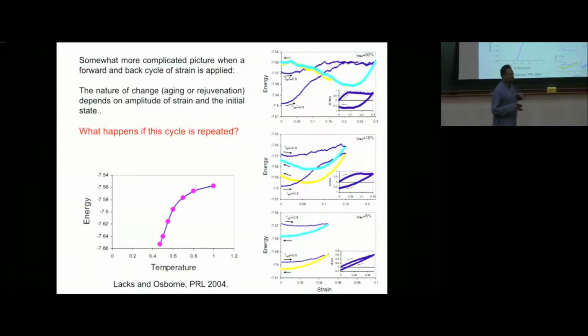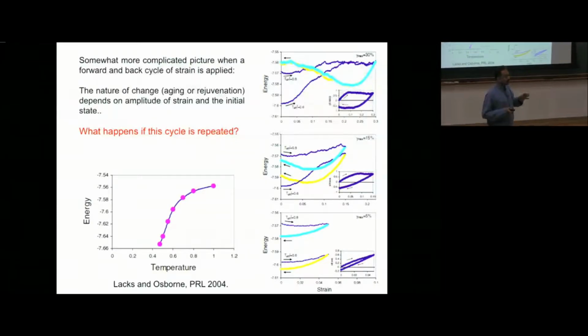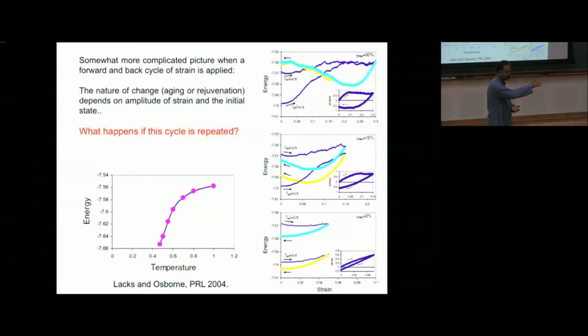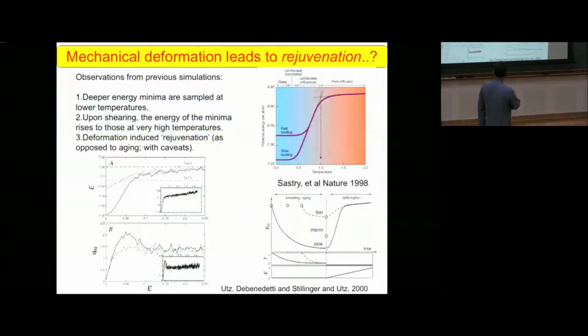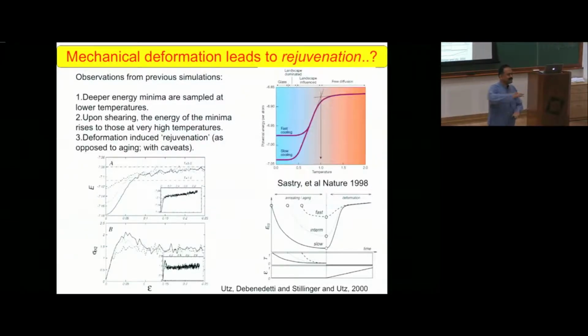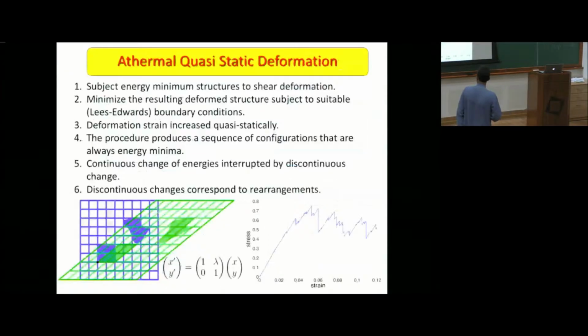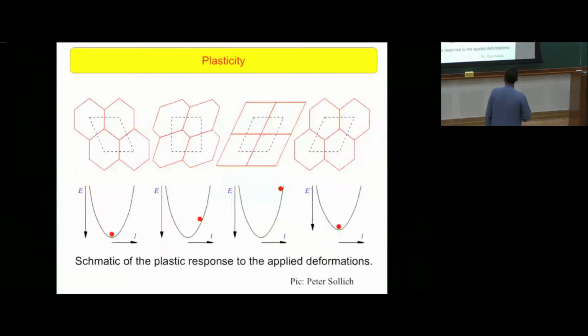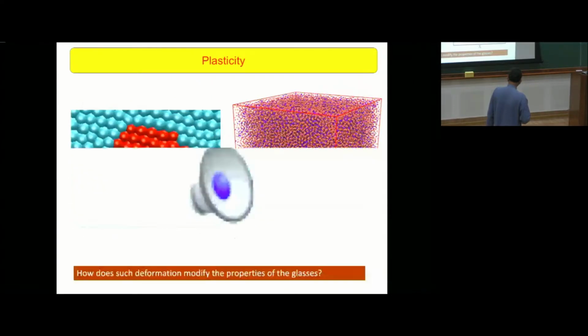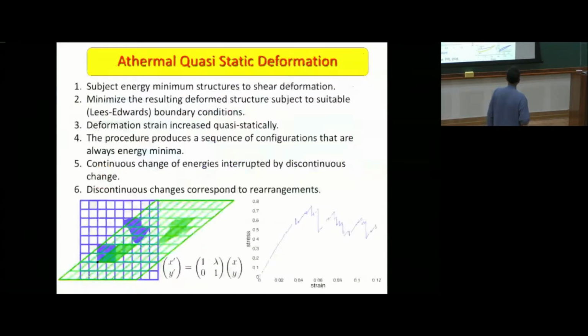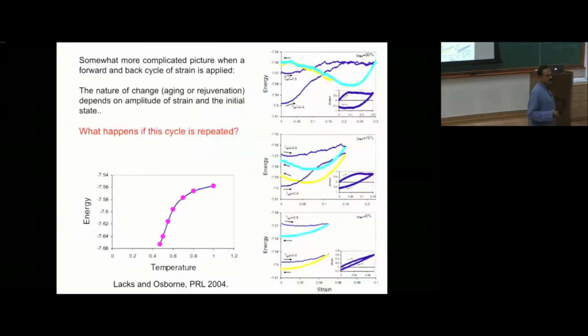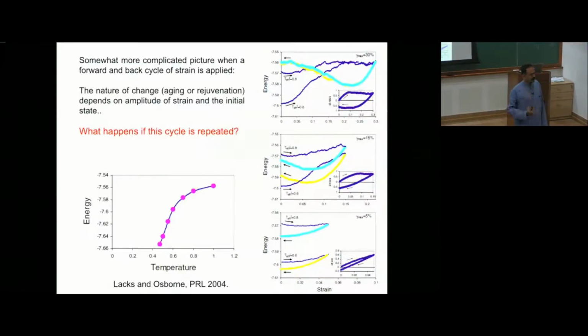But then you can say, instead of pushing my system in one direction, and this is how we got started on this, because if you look at this curve here in the energy, right? In the initial part, the energy is not really increasing. I'm just adding a strain component to the energy, right? This increase in the energy is because I'm still sitting in the same energy minimum, but because I'm straining the system, I'm adding an elastic energy.